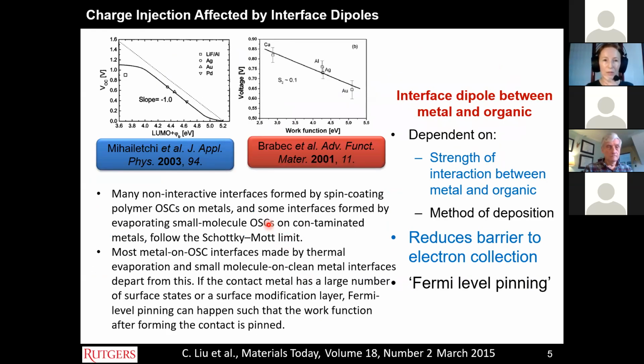Just before I get into our own work, I want to talk as well about charge injection at the interface. In polymer materials, usually non-interacting interfaces are formed when we spin coat the polymers on metals. And so we create what would be called a Schottky-Mott junction. So when we think about how the open circuit voltage, for example, of an organic solar cell changes with the work function of the electrode, or some difference between the LUMO that's affected by the work function of the electrode, you have a very significant change in the open circuit voltage with that. So that's very sensitive to the change in the work function of the metal. That's for the polymers spin coated on metals.